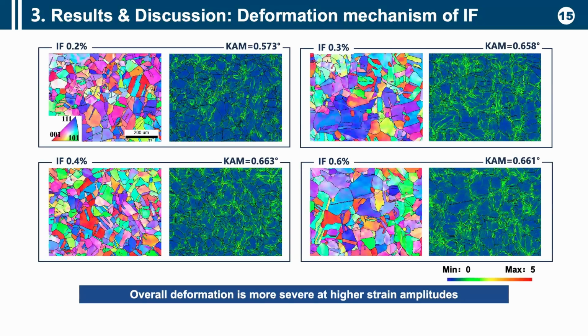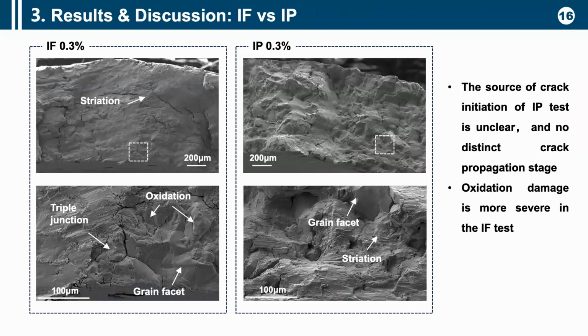And this is the IF deformation mechanism with different strain ranges. You can also see the KAM value increases as the strain amplitude increases. Also for IF 0.3% and IP, we compare the two pictures. We can see the oxidation on the surface and the grain facet striation, so it means the oxidation damage is more severe in the IF test.